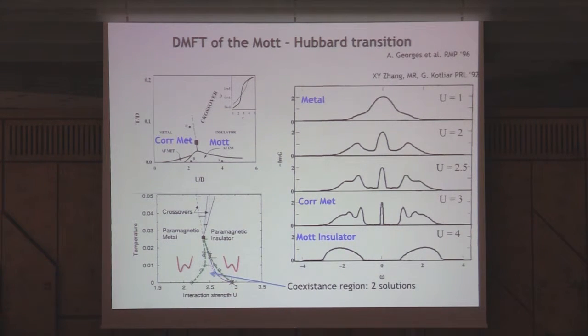A very surprising thing that happened was that if you start from the insulating side, and you start lowering the value of u and following this solution, what you find out is that for these same values of parameters, you can still have an insulating solution with the two Hubbard bands just getting closer and closer. And that goes on until the two bands touch and you destroy your insulator. So there is a region there in parameter space for a half-filled system, which is where there are coexistent solutions, pretty much as in the Ising model, where at low temperature you have the two ferromagnetic solutions.